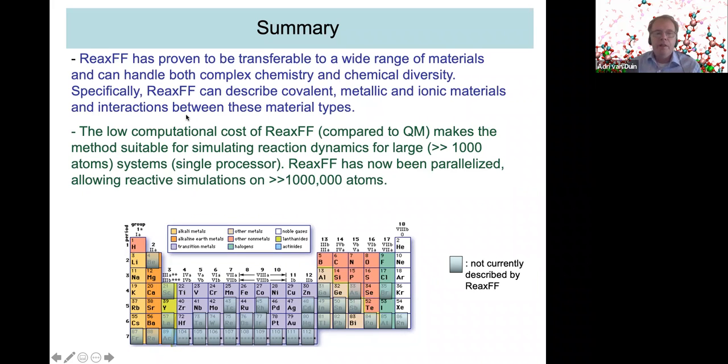So ReaxFF is not as accurate as quantum mechanics. We try to get it as close to the quantum mechanics accuracy as you can, but it allows you to run much, much larger systems. And quite often in the type of comparison that you'd like to draw, the size of the system is very important because there's clearly many things that you cannot really evaluate at a small, let's say 100 atom system. You really need to go to larger systems to express vacancies, to express grain boundaries and the migration over time.